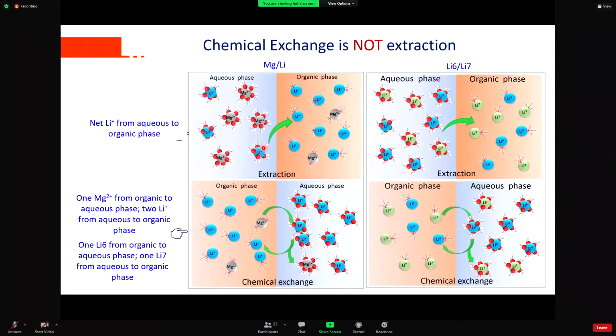For extraction, the extractant is not saturated or is not in equilibrium with the brine. So there is net lithium coming from the brine to the organic phase. But for the chemical exchange, the organic phase and the aqueous phase are in equilibrium. So if there is one lithium coming from aqueous phase to the organic phase, the magnesium will come from the organic phase to the aqueous phase. This is the same for lithium isotope separation.